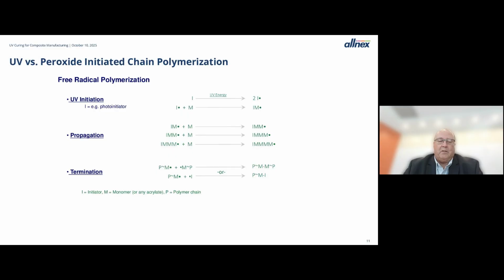So I bring it up because often the philosophy is more is better. And in the case of UV, people are tempted to throw in more and more photoinitiator to make things happen faster. But what you're doing is you're increasing the termination rate. And so you may cure faster or you may solidify faster, but you're making a different polymer. You're making a shorter polymer, and that could adversely affect your end properties. So the caution here is to use photoinitiator sparingly and not fall prey to the more is better philosophy.